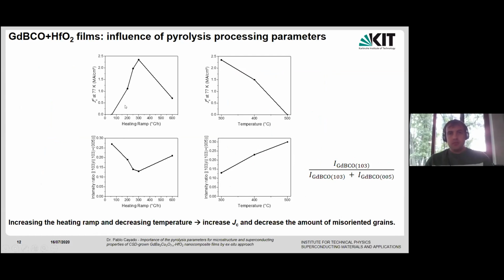What I am showing here is what happens when we use this single-step pyrolysis and we modify either the heating ramp or the final temperature. You see that the JC and the ratio of these misoriented grains, calculated with this formula here, change with changing either the temperature or the heating ramp. So this means that by careful adjustment of these processing parameters, we are able to increase the JC or improve the performance of the films, and this increase of the JC seems to be correlated with a decrease in the amount of misoriented grains. So this is what we could conclude from these experiments.